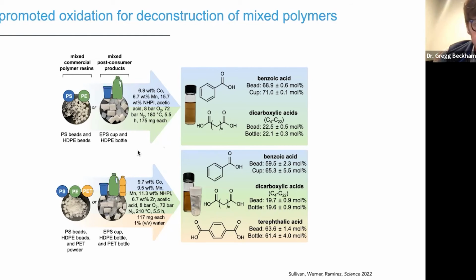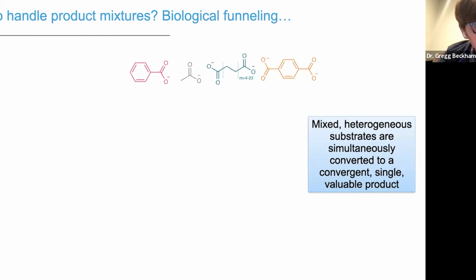When you combine all three plastics, now running at the conditions optimal for PET, again, 5.5 hours, you can see, again, a slightly lower yield of DCAs from polyethylene, but similar yields for benzoic acid and terephthalic acid in this mixed plastics case. So that's quite cool. But then we make this mixture of products. And so how do we deal with that?